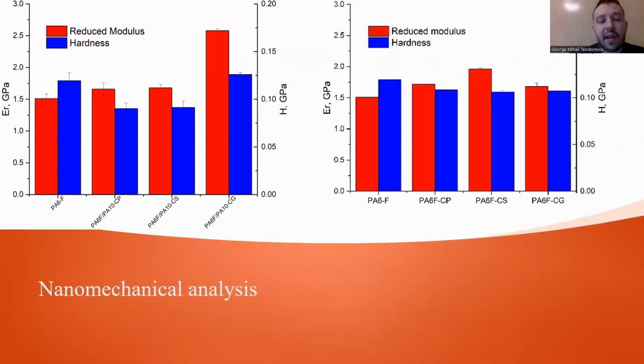From a nanomechanical point of view, both series showed a slight increase in reduced modulus by 2 to 5% compared to PA6F. In terms of hardness, a decreasing trend can be observed in composites with treated ash compared to PA6F. The exception is the sample with ash treated with silane from the PA6-PA10 series, where the hardness increases by 41%. This sample also shows the highest value for the reduced modulus.